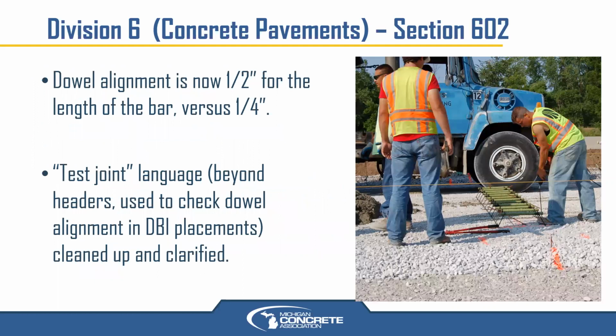Another change that we're going to see is the dowel alignment for the entire length of the bar, which is an 18-inch long bar that you see in the basket there. Dowel alignment now is going to be required to be a 1/2 inch over that 18 inches as opposed to a 1/4 inch. That is more in alignment with what other states around us are doing. This is most likely a result of MDOT's participation in the National Concrete Consortium, where a number of states get together, state DOTs, along with industry, and talk about best practices and the latest and greatest. And MDOT has realized that other states have been using a 1/2 inch alignment over the 18-inch bar for a very long time, and with very little problem as a result of that.